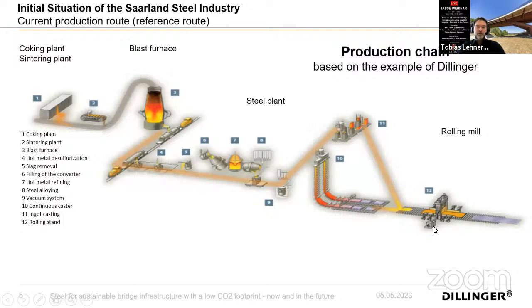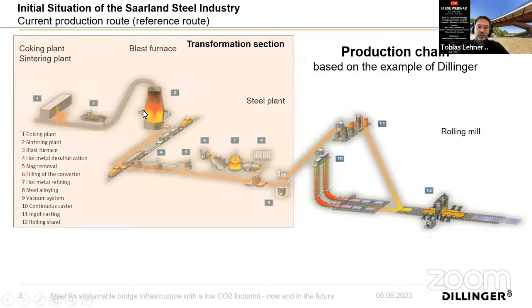And I will just shortly show, because it was already explained before, what is the initial situation in such a blast furnace mill. So we have a coking plant, we have a blast furnace, and the basic oxygen furnace, and the emissions are mainly coming from the blast furnace, where we need the coal to reduce the iron ore, so to take away the oxide. And if we combine the C from the coal with the oxygen from the iron oxide, we will end up with CO2 emissions. And then in the next step in the steel plant, it's a basic oxygen furnace. So we blow oxygen on the liquid steel, or iron in this case, and then take away again the C, the carbon, and we again have CO2 emissions. So these two processes are responsible for most of the emissions in such a primary, currently blast furnace, primary route.